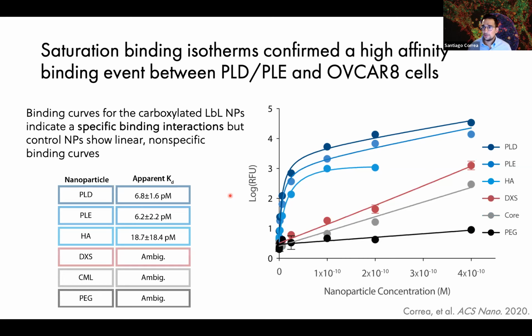Now, in contrast, if we look at some other nanoparticle systems, including another LBL nanoparticle here shown in red, this one coated with that dextran sulfate, or our unmodified core material, or even just pegylated nanoparticles, we see a linear curve that is the hallmark result if you have non-specific interactions. And so in general, we see a very stark distinction between these specific binders and these non-specific binders.